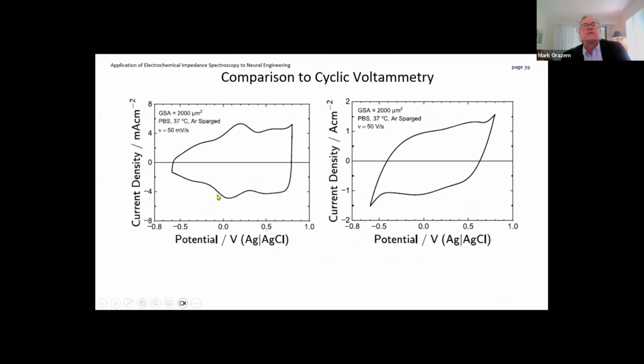The last thing I want to show you with this one is to look at cyclic voltammetry. Cyclic voltammetry is commonly used for these kinds of electrodes. From this, we can calculate a charge focusing on just the negative current in this voltammogram. These voltammograms, this one is at 50 millivolts per second, this one is at 50 volts per second. Then the capacitance we get is this Q divided by a delta V, and the delta V has to be corrected by the ohmic resistance.